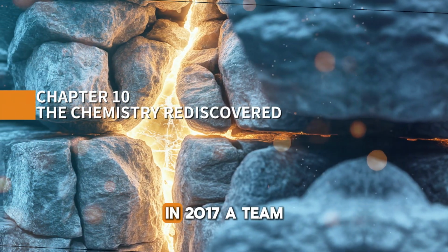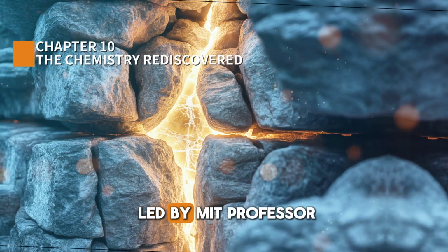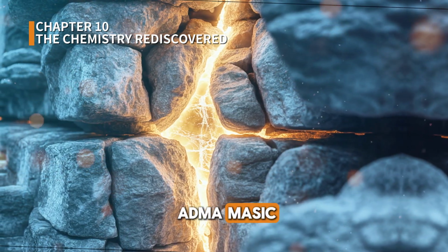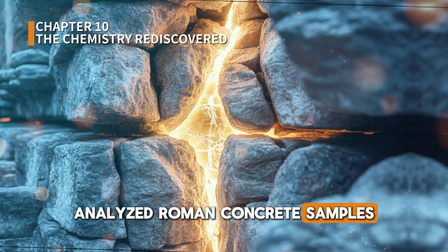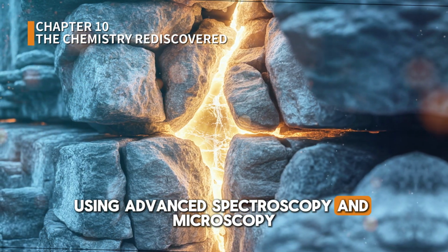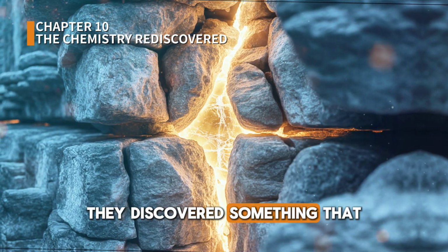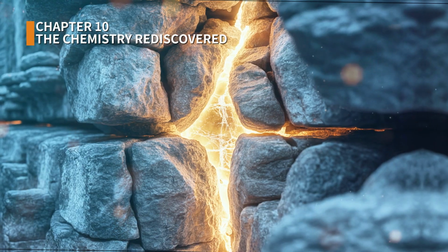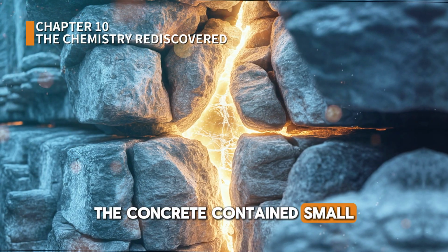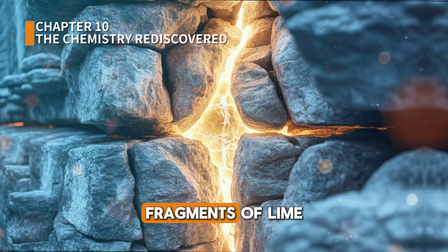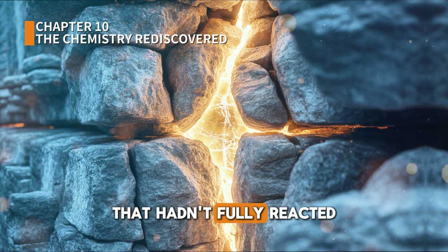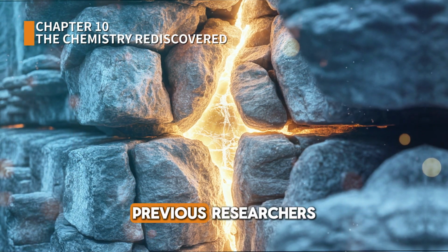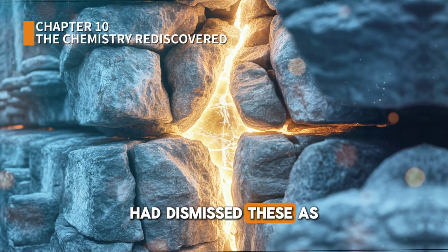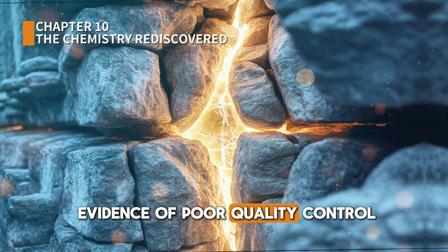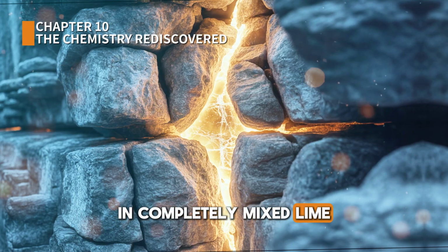Chapter 10. The Chemistry Rediscovered. In 2017, a team led by MIT professor Admir Masic analyzed Roman concrete samples using advanced spectroscopy and microscopy. They discovered something that had been overlooked. The concrete contained small, white inclusions throughout, fragments of lime that hadn't fully reacted during mixing. Previous researchers had dismissed these as evidence of poor quality control incompletely mixed lime.